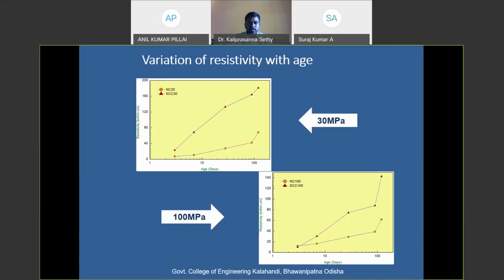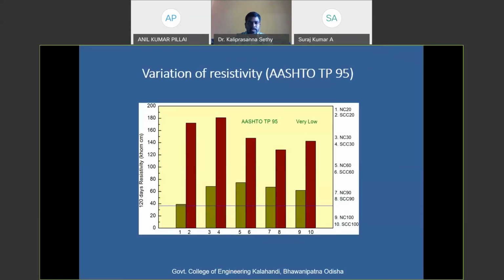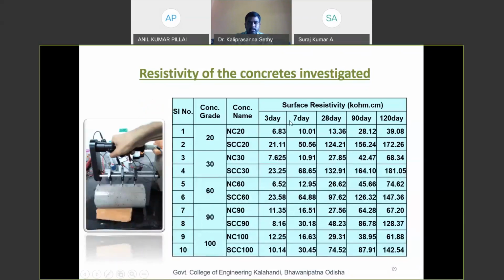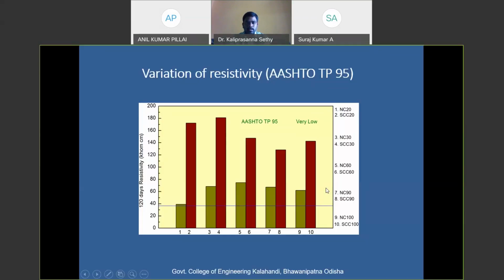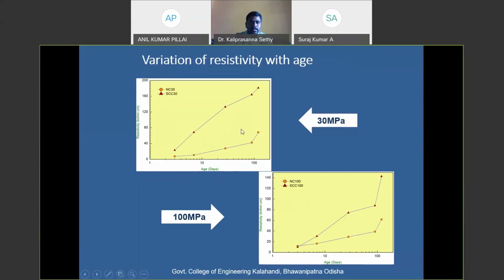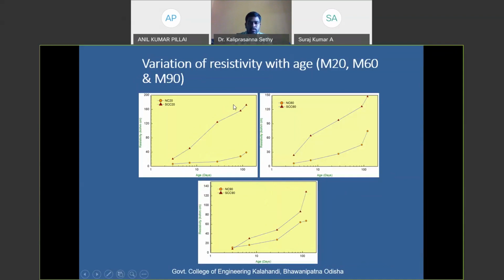Let me show you the values first. These are the readings taken at 3, 7, 28, 90 and 120 days for all the normal and self-compacting concretes. Here is the graphical representation of the results plotted between age and resistivity. All the self-compacting concretes are showing very good resistivity results compared to our normal concrete. And here also for all the cases we are getting a very good resistance towards chloride ion penetration.